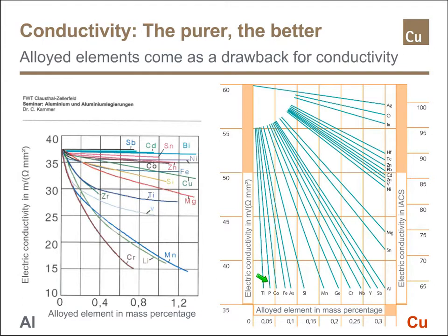Sulfur is unfortunately not on this plot here, and it remains to be noted that we have a range from 0 to only 0.3% mass percentages of quantity of alloyed elements. Now, the effect is not so dramatic with aluminium, as you see here. You have here a range up to 1.2 percentage points, and you see that some elements really have approximately no impact upon the conductivity. Some have a considerable impact, but still much less than we have for copper.